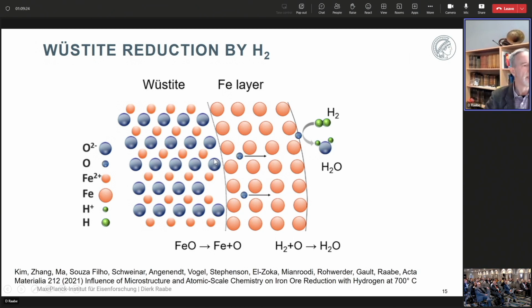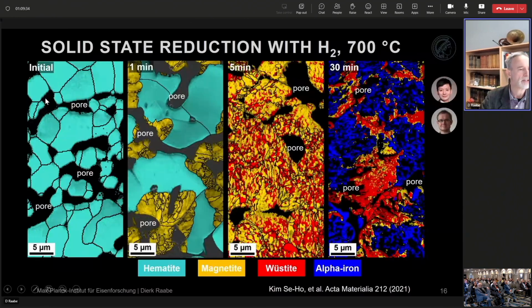When we look in the EBSD, you can follow this hematite pellet structure. You see it's a sintered polycrystal with a lot of inherited porosity, around 15 to 20%, from the pelletizing process. And then the first reduction after 1 minute at 700 degrees, you see something like, I would say, classical Avrami type of surface nucleation plus growth. It's incoherent interfaces, mainly incoherent between the magnetite and the hematite. So there's not much surprise here.